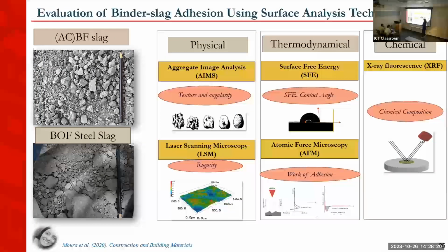For thermodynamics, we measured the surface free energy of those two slags to see if they were different. We also checked the wettability of the slag by the binder by measuring the contact angle. And we also used AFM to check the work of adhesion between the binder atoms and the slag atoms. Finally, we checked the chemical composition of those two slags by using X-ray fluorescence.